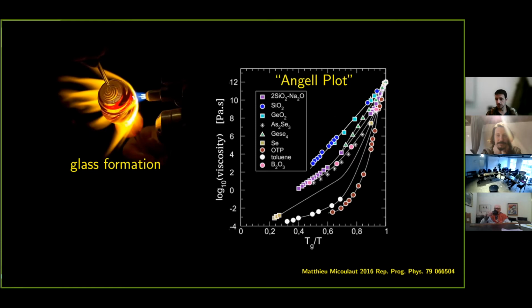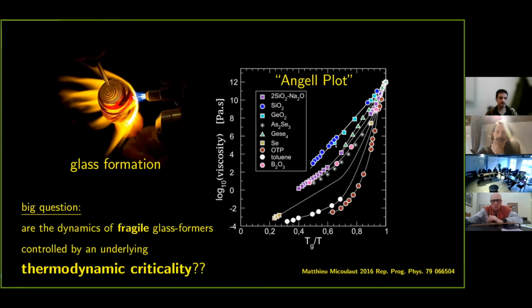When you do this, what you find is that some of the materials, like silica, follow a straight line, indicating what we know as an Arrhenius activation rate. But some other materials, such as OTP, have a very curved shape when represented in this way. And these differences between different liquids gave rise to this big question about glass formation, whether the dynamics of fragile glass formers, the ones that are non-Arrhenius and don't obey this straight line in this representation, are controlled by an underlying thermodynamic criticality? And this idea was also inspired by results from spin glasses, as we heard just now from John.